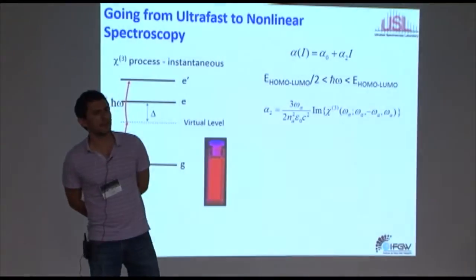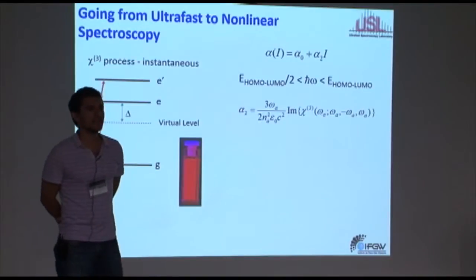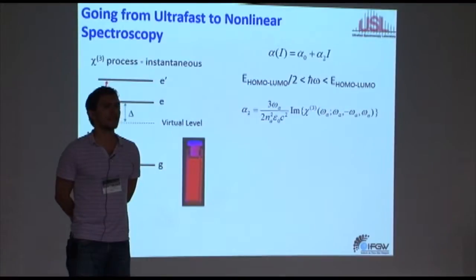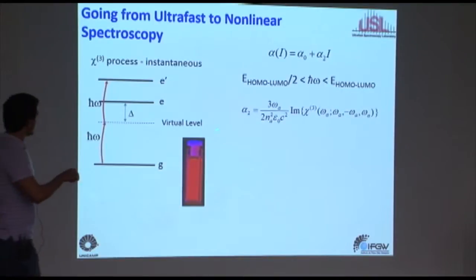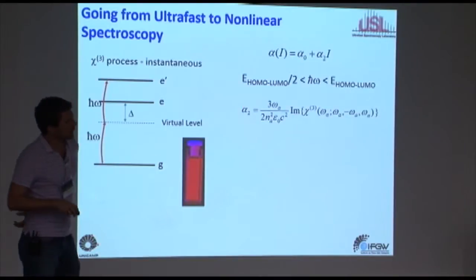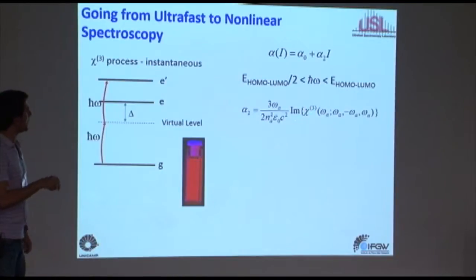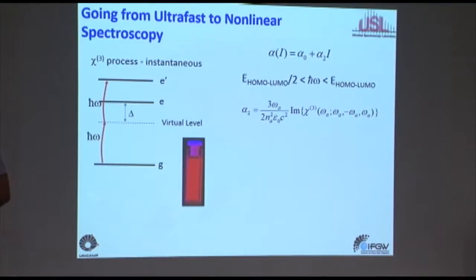For applications, Sid wants materials with large nonlinear refractive index and small nonlinear absorption. I tell Sid: if you find a material with large two-photon absorption, send it to me — that's what I want. Two-photon absorption might seem like it should be chi-2, but it's actually chi-3. It's the imaginary part of chi-3 that happens at omega, because it involves omega minus omega plus omega. In physics terms, two-photon absorption involves a virtual intermediate state: you want to go from the ground state to an excited state, passing through a dashed — non-resonant — intermediate level.